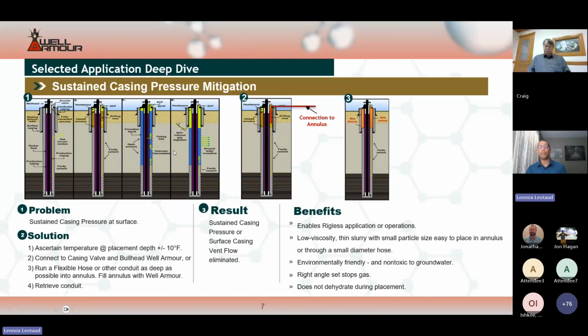So sustained casing pressure can present itself in a couple of ways, but for the case where the production casing annulus is not cemented all the way to surface, which is the case for most shale play development wells here in the US, what some operators are doing is they are running a flexible hose. It could be a 1/2 inch or a 3/4 inch hose through the wellhead valve, and they will run it as deep as they can get it, and they pump a weighted brine. It could be a 10 pound per gallon brine, a 10.5, 11 pound per gallon brine or higher, and they do that to try and add some additional hydrostatic pressure to lower that sustained casing pressure.